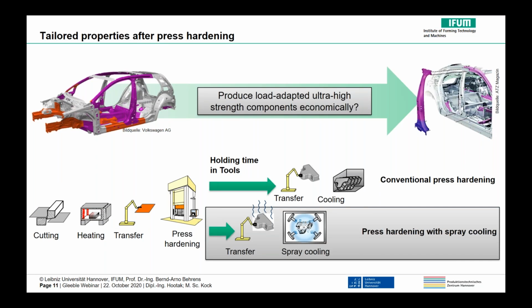Press hardening is a process of hot sheet metal forming, which is mainly used in the automotive industry. In this process, a sheet is heated to a temperature of over 900 degrees Celsius and cooled in the tool during the pressing. This produces a martensitic structure with high strength.